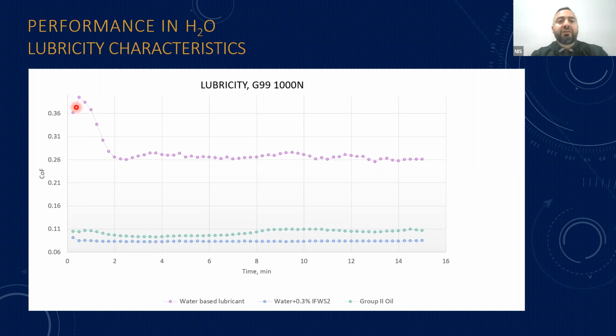A very important point here: in a G99 test, a pin or ball goes on the same round track for 15 minutes, and you're measuring the friction. So you see initially with a commercially available water-based lubricant, metalworking fluid, friction goes up. And then, of course, when friction goes up, temperature goes up in the contact area. And when the temperature goes up, a chemical reaction happens with certain additives and components in that water-based lubricant, and it starts generating tribofilm, and friction goes down to a certain point.